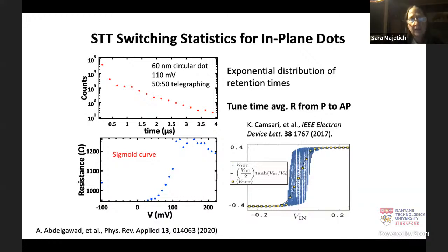What we think is that this Arrhenius law behavior works down to sort of tens of nanoseconds. When you get into that regime, then an Arrhenius law for the energy barrier really isn't appropriate, and you would have to do the modeling with Landau-Lifshitz-Gilbert theory. But even in the nanosecond timescale dynamics, the probabilistic approach would work. It's just that the Arrhenius law wouldn't be appropriate anymore.